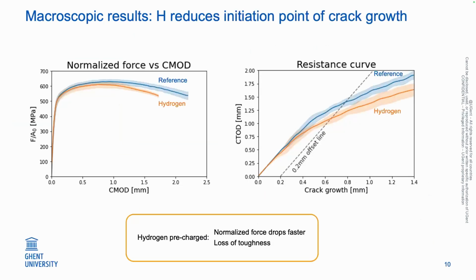So if I now go to the results, for the reference test, we did 6 specimens. For the hydrogen one, we did 5 already. And we see in the normalized force that there's a slight drop for the hydrogen pre-charged specimens. But most importantly, we see that the normalized force drops faster than for the reference specimens.